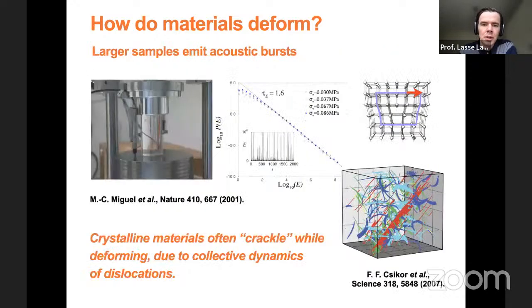If you look at the stress strain curve, then you can also look at these large samples where the stress strain curve usually is smooth, but you can also monitor this plastic activity in different ways. So one is to record the acoustic emission that is coming from the deforming sample. So here, for instance, is an ice single crystal that you compress, and then you can attach some acoustic emission transducer, and you can look at the energies of these acoustic emission events that are emitted from this deforming sample, and these will end up having this kind of power law distribution, so a very broad distribution with a wide range of scales.